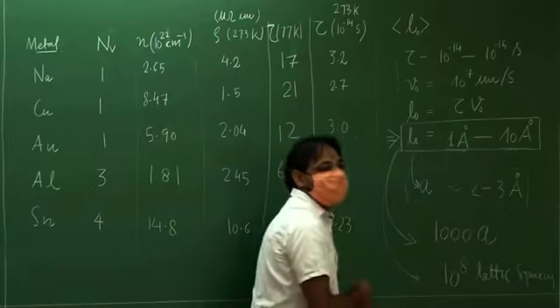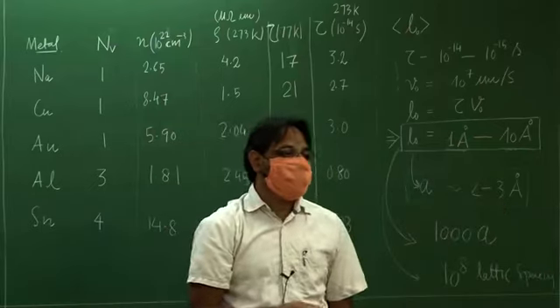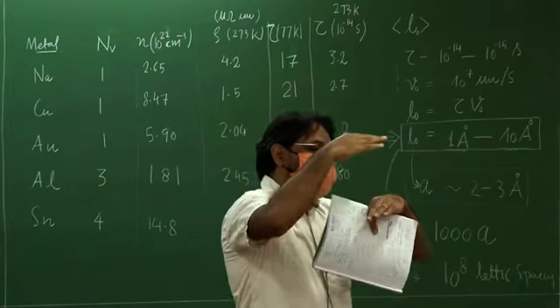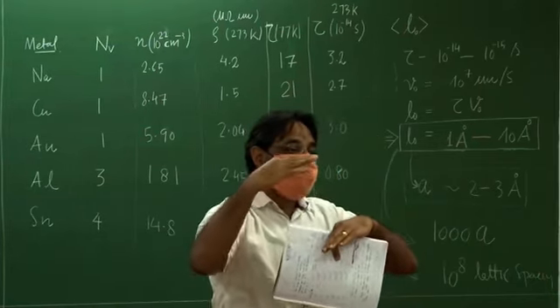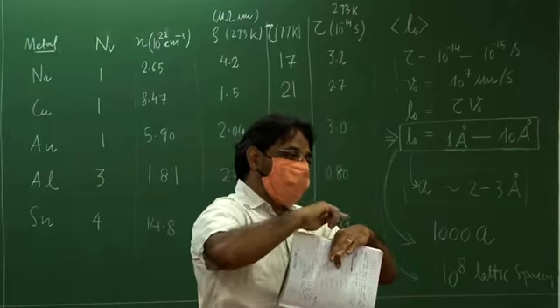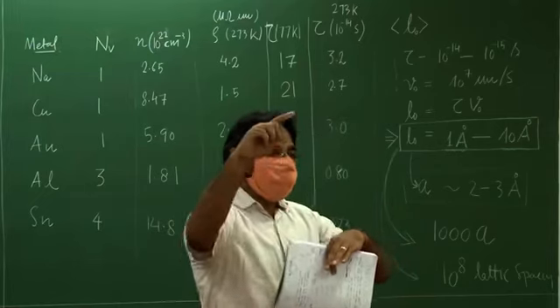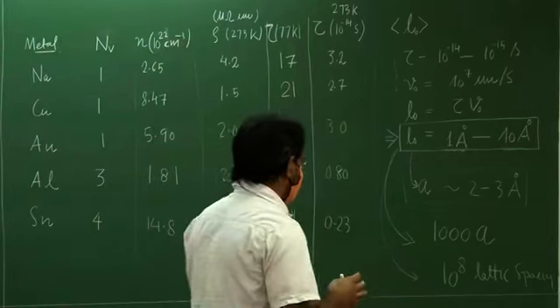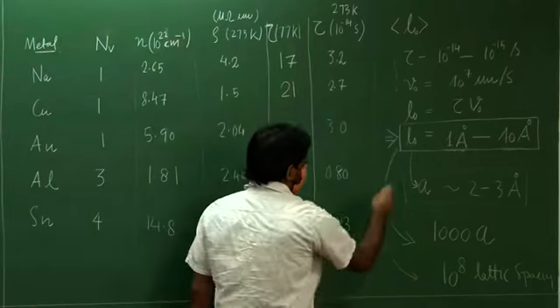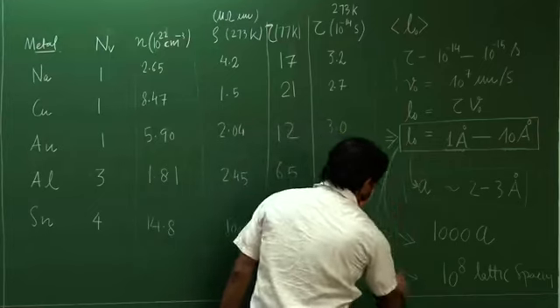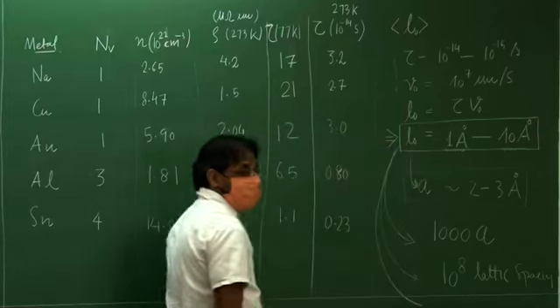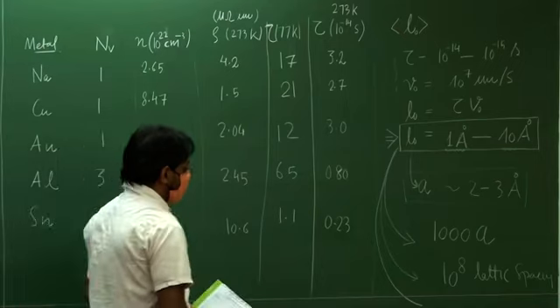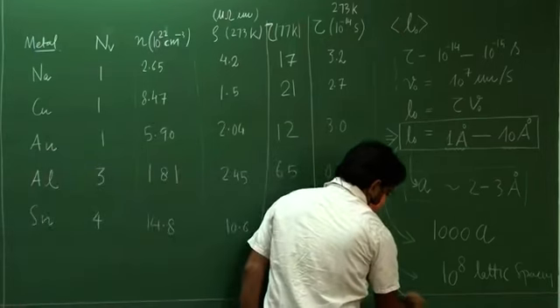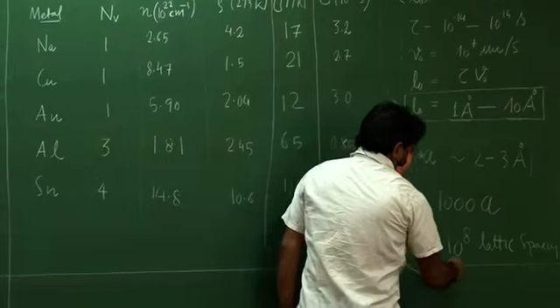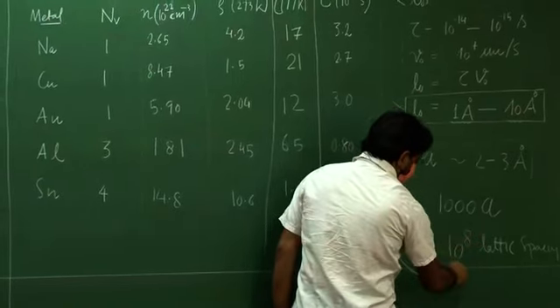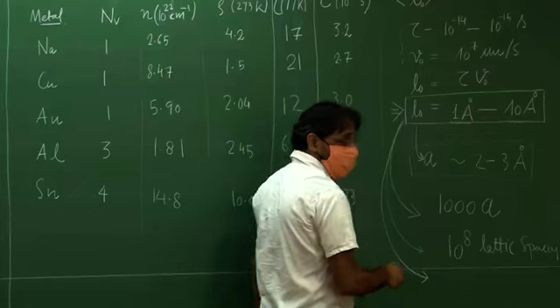Now 10 to the power 8 is certainly huge, and in some cases it would just be the dimension of the material. This is called ballistic transport, where the electron sees only the boundaries of the material. So the material is so pure. So it's not just the ionic cores that are playing a role, but there is something else. And if you can take care of that something else, then your mean free paths get larger and larger.